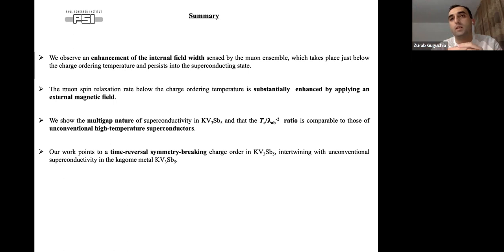But when we apply a high magnetic field, then we can exclude the change of the electric field gradient, because the magnetic field creates the quantization axis for the nuclear moment, so it's fixed. So the only thing that can change is the electronic contribution, which would come from the orbital currents. And we still see that change happening at the charge density wave transition temperature, right? So we kind of favor that orbital currents, or whatever weak fields we see, have the same onset as the charge density wave, but I cannot say which one is driving or which one happens first. Their onset is the same. This is what I can say.